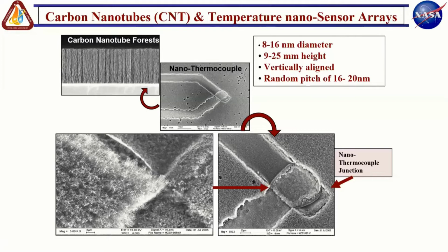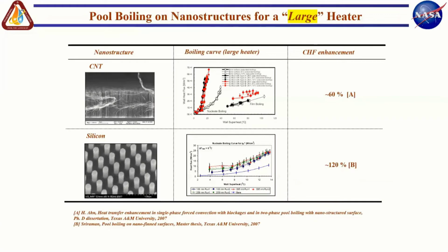We actually worked with 2 different heights of carbon nanotube coatings initially, and they were pretty well vertically aligned, as you can see in the picture in the top left that shows it like a toothbrush. It's more like a forest of carbon nanotubes. And so we put this in our boiling rig, and we did boiling experiments with PF5060, which is a refrigerant made by 3M.